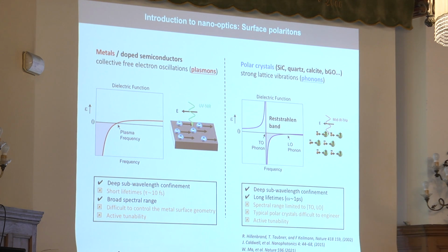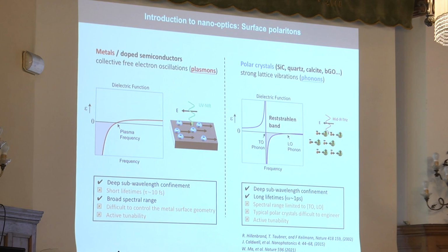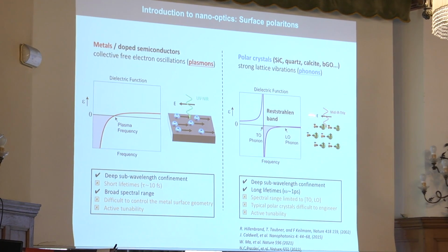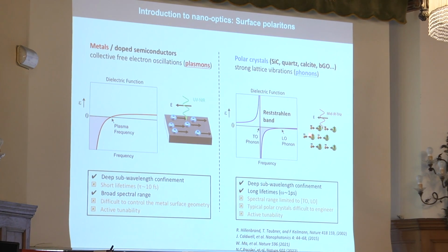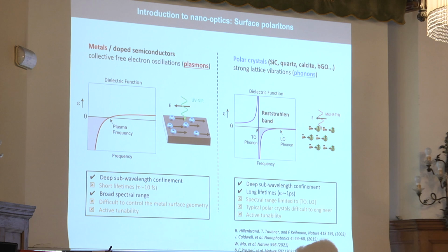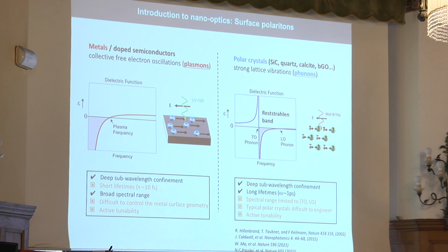But in this case, the material that has the negative permittivity is not so because of free electrons like a metal, it's because it's a polar material, meaning that it's a lattice containing two very different atoms with very different electronegativity values, and therefore the carriers are closer to one of the atoms than the other, and then it creates a tiny dipole between them. And this tiny dipole can react to the incident field, screening it out again, so creating a negative permittivity at the same time, and therefore fulfilling the conditions to support these surface waves.